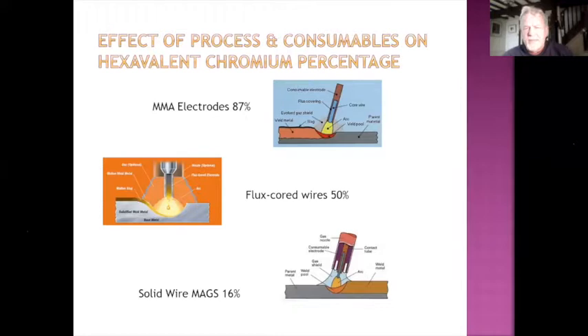Here we have an example of welding stainless steel, hexavalent chromium content, where this is the issue with this potential for a carcinogenic substance. If we go with a conventional manual metal arc electrode, then there's an 87% percentage on that particular process. If we move to flux core wires, it reduces down to 50%. If we go to a solid wire MIG, we're down to 16%.